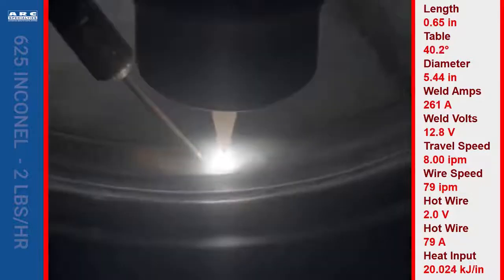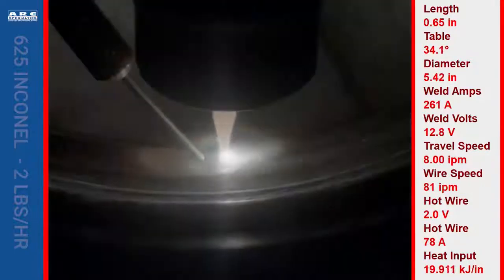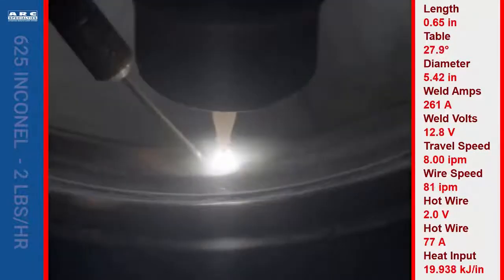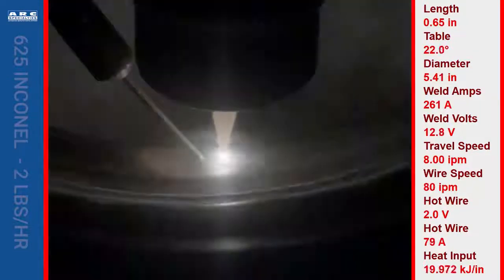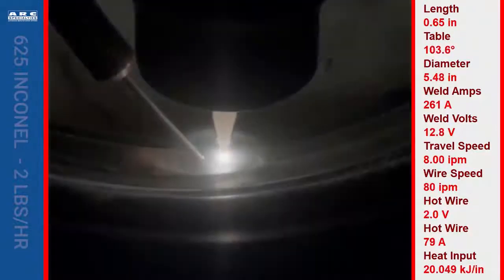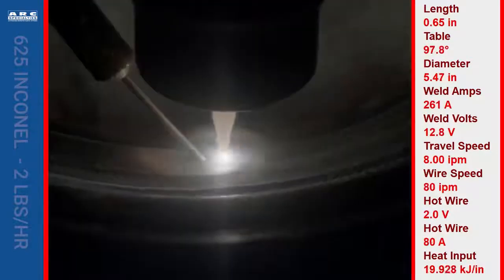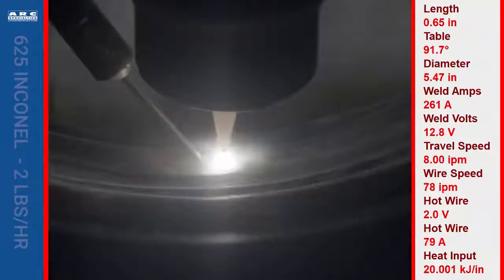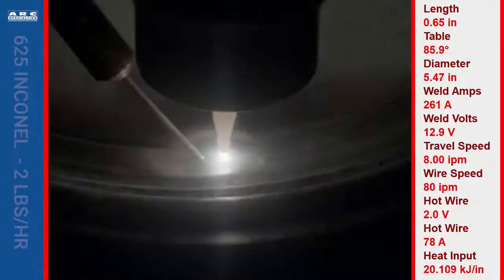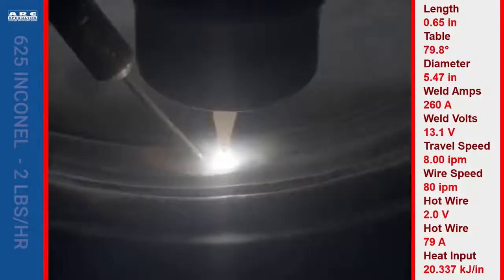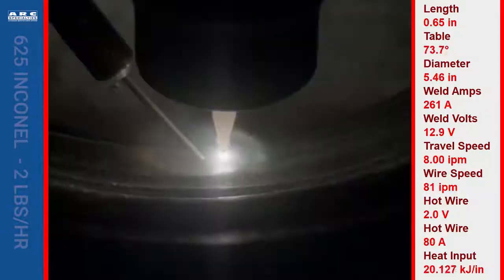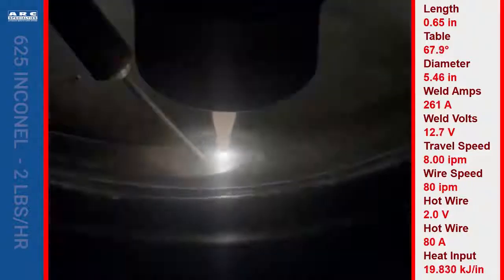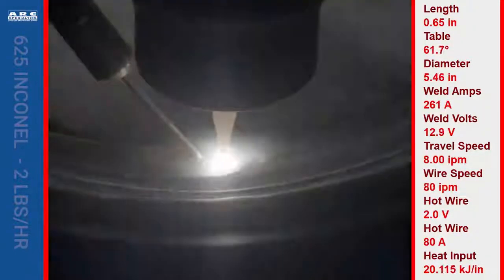Our travel speed is 8 inches a minute, and our wire feed is 80 inches a minute of .045 wire. The hot wire is running at 2 volts, which puts in about 79 amps of power. So if you multiply the 2 times 80, that's not that many watts of power, but it's a significant contribution, and it allows us to reduce the overall heat input for the whole weld. So we're only running this part at 20 kilojoules per inch, which is a relatively low heat input.